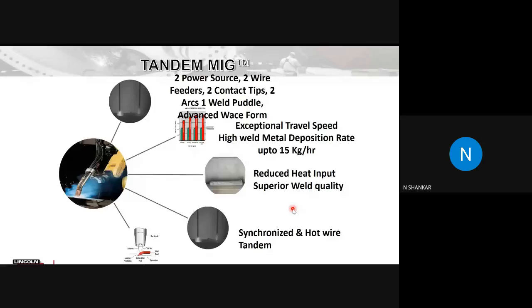The other way of looking at increasing deposition is having two wires in the same arc. You have heard about tandem MIG. Tandem MIG is a process that has been extensively used now in a lot of industries. All the earth moving manufacturers like the JCBs and the Caterpillars have started using tandem MIGs. Their tier 1 suppliers have also moved to tandem MIGs. It means two power sources welding at the same time in a single puddle, which means there are two power sources, two wire feeders, two contact tips, two liners, two arcs, but one single weld puddle.